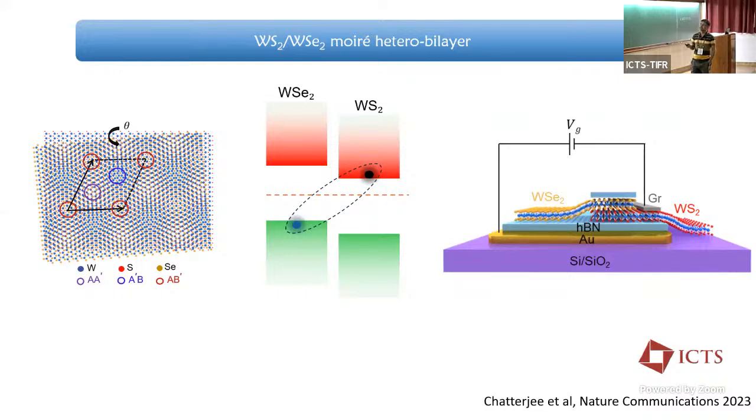So this is the interlayer exciton. Obviously, this interlayer exciton has much lower oscillator strength compared to the typical intralayer exciton that we talk about in these materials, where the electron and the hole stay in the same layer, simply because the wave function overlap reduces because of the spatial gap. Also, there are debates, but it's not guaranteed that they are momentum direct.